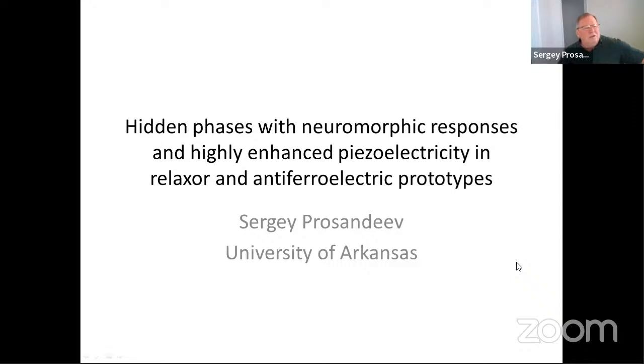This is an integral characteristic which we suggested, the strength of the connected cluster. So there is a cluster connecting one border of the supercell with the opposite border. And this cluster gets more and more ions in it when we go from the lower hidden states in my picture to higher hidden states. So this is just the growth of the connected cluster, first of all, which, if you look by eye at the picture, you do not see.